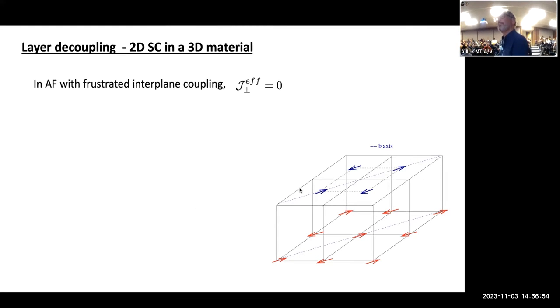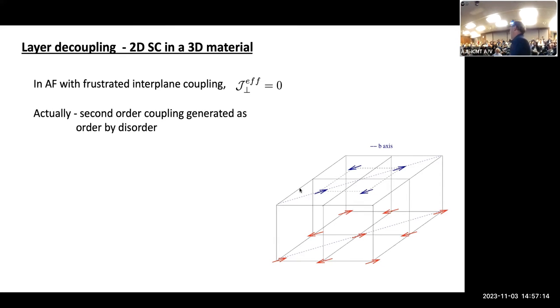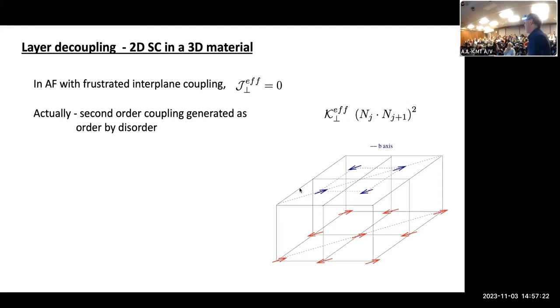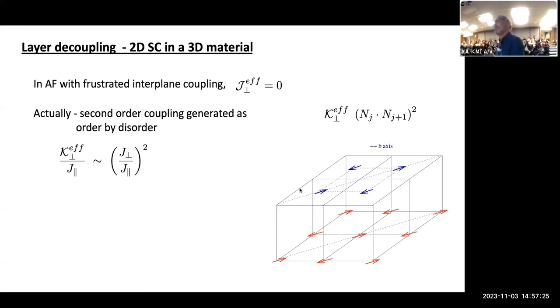So they're decoupled from each other. That's why one's able to see such good 2D antiferromagnetism over a broad range of temperature above the Néel temperature in lanthanum cuprate. You know, since Shivaji's here and he likes order by disorder, indeed, there are higher order couplings that are always generated. For instance, couplings of this form, but those are going to be small in proportion to the square of the ratio of the interplane to the in-plane coupling.